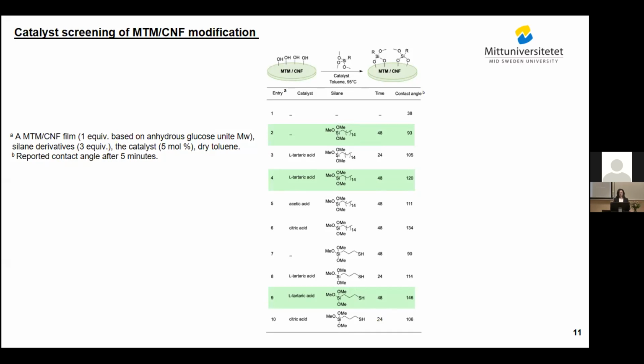Also, we can see in entry 3 that when we had a catalytic amount of this organic acid, we could reach even higher contact angle value compared to without catalyst and in 48 hours. And when we did this reaction with the mercaptosilane, then we got an even higher value. Also, we did this reaction with citric acid and acetic acid, and with citric acid, we had a higher value compared to tartaric acid.